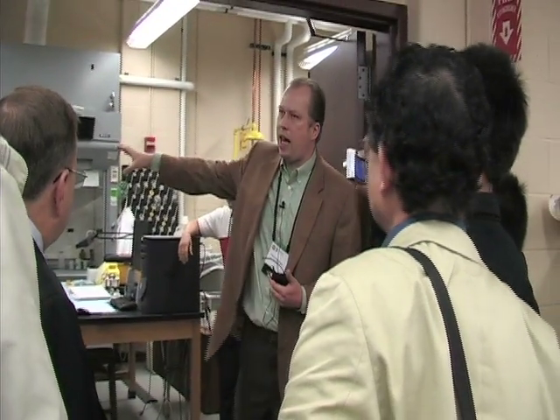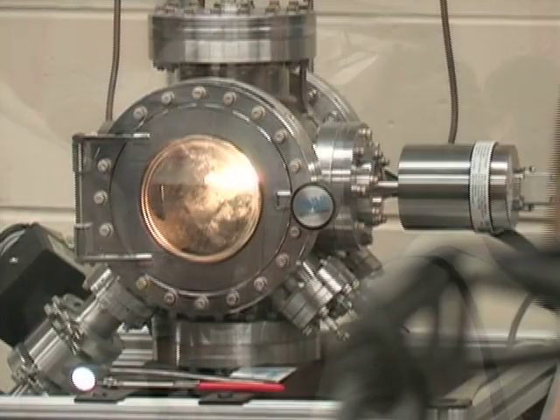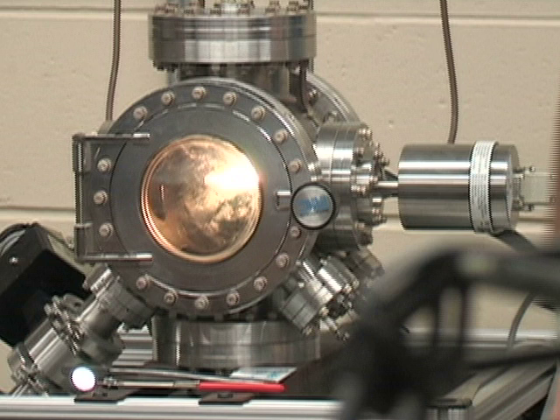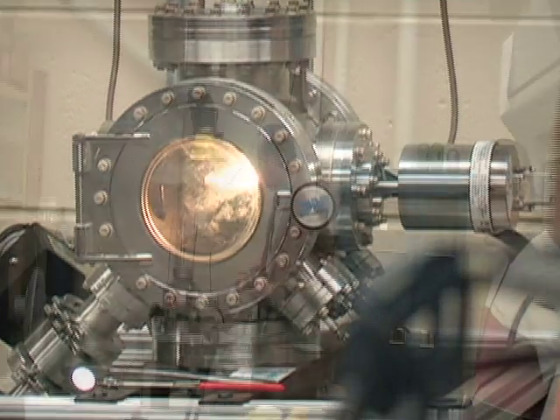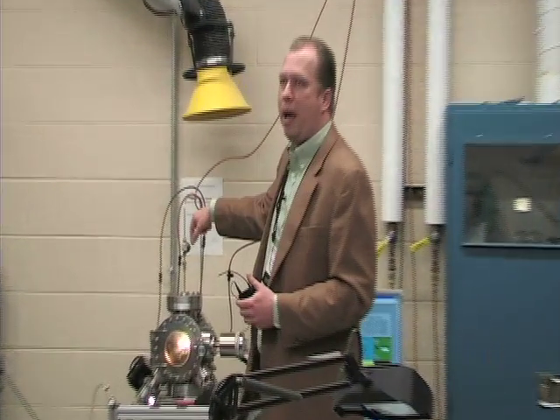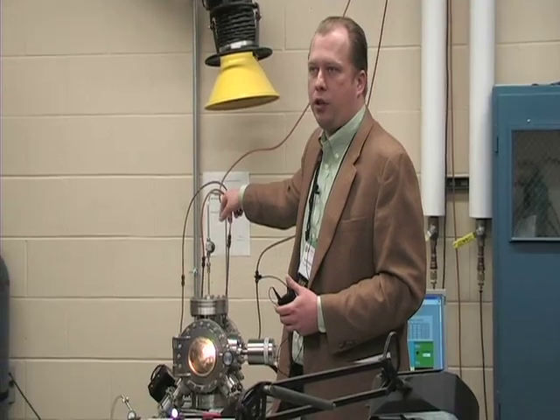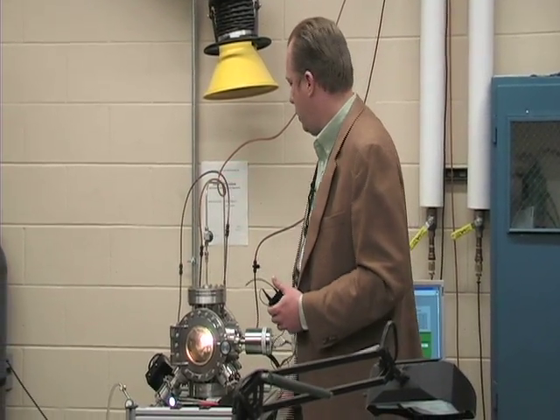We have a small chemical vapor deposition reactor. It's just a very small system for research. We generally grow on one tool at a time. However, this process, as you may or may not know, is completely scalable. They're commercially available 16-inch diameter chambers where one could put hundreds of certainly micro tools at a time and coat them. You flow in methane, excess hydrogen, just 4 to 6% methane in hydrogen in here.